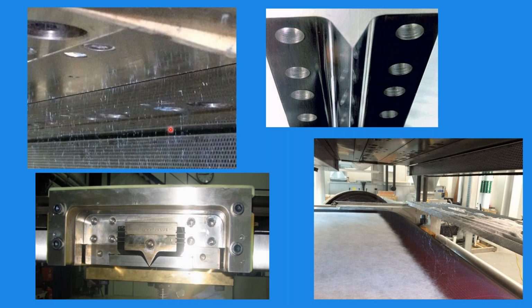Now what's interesting is you see this random motion where you saw the spunbond was a lot less chaotic, and this chaotic motion is really important because as the fiber comes out, it whips left and right very, very fast, and that actually helps draw it down. Not only does it draw it down, but it makes a fiber that has two different fiber sizes, so it's kind of narrow in one spot, thicker in another, which actually kind of helps some of its properties.